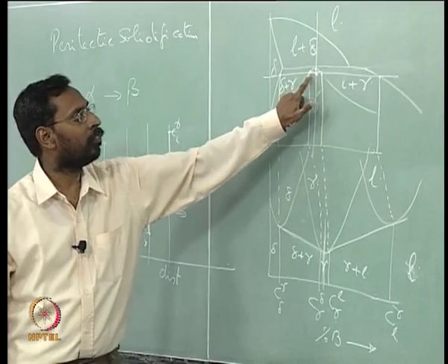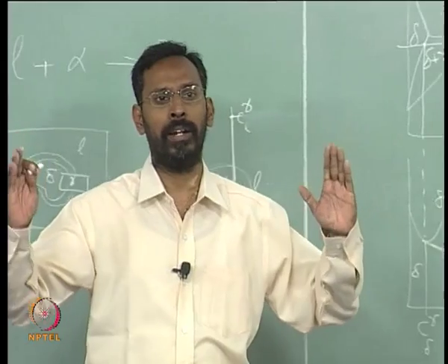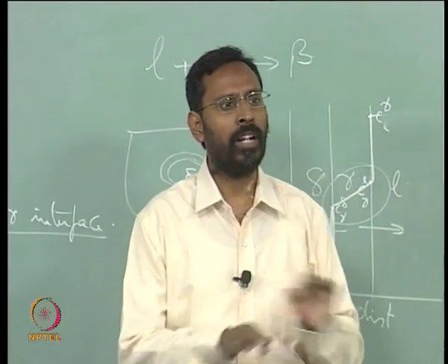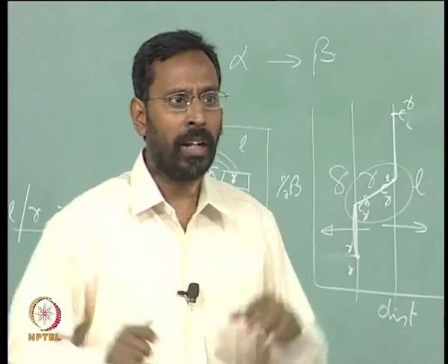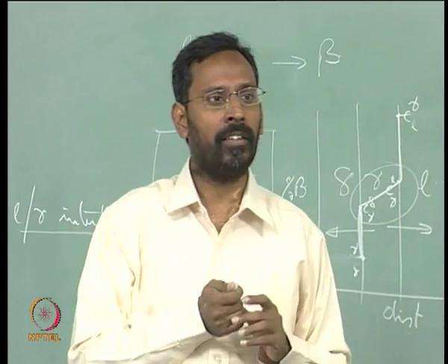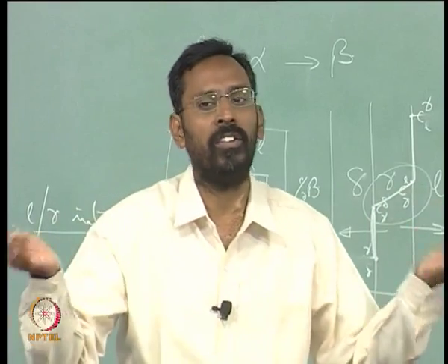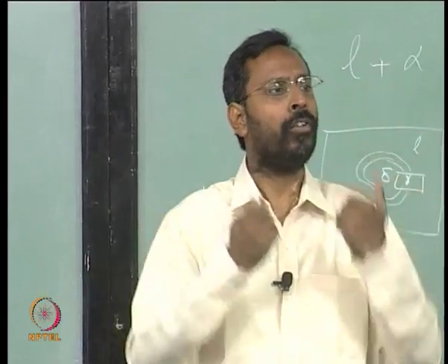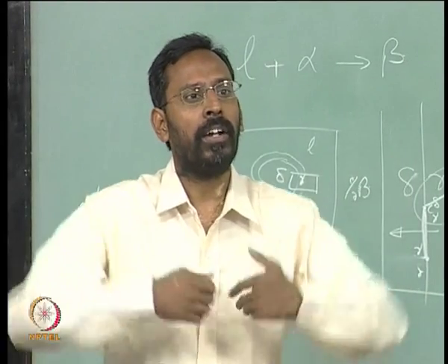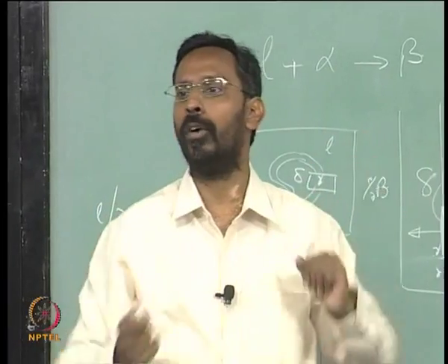Because it is falling within the single phase gamma domain, at that temperature what is stable is only gamma in principle. So, whatever liquid and whatever delta is there at that temperature at a particular point of time, they are only metastable, they are not stable. So, in principle that liquid wants to get transformed to gamma. Similarly, delta also wants to get transformed to gamma.